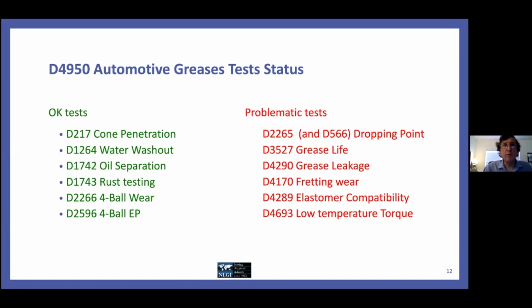We also looked at D3527 grease life. The repeatability and reproducibility of that test method is poor. The grease leakage test, again, uses the same apparatus as the D3527, and the question for that is, is that test method still relevant in today's world? Fretting wear was known to have a lot of issues, especially with repeatability and reproducibility, and there were also some issues related to equipment and the supply of bearings.